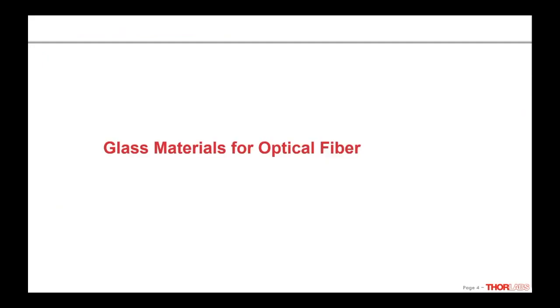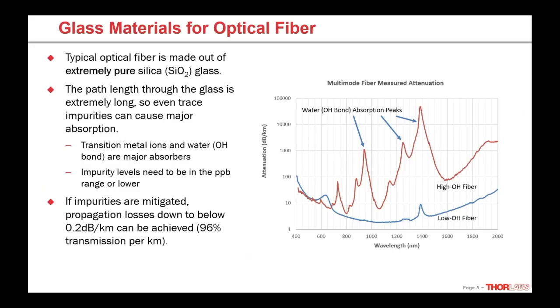It all starts with the materials we're going to use for optical fiber. The most common fiber — the vast majority of fiber — is made with extraordinarily pure silica glass, SiO2. It's very important for this glass to be virtually completely free of any impurities. The reason for this is that as light passes through fiber, comparing it to a lens or bulk optics, the fiber has a much longer path length — much more distance where the light needs to travel while it's inside the glass.